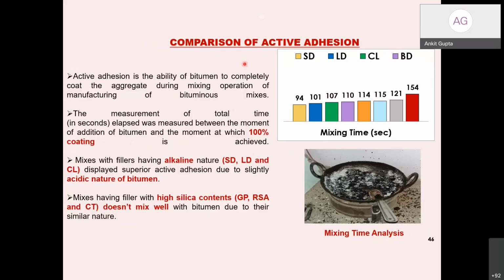Active adhesion is the ability of the bitumen to completely coat the aggregate during the mixing operation. When we mix the aggregate with the bitumen, how fast they coat the whole aggregates with the bitumen, that is the time of coating, basically what we measure. Obviously it is a visual test that we do in the lab. The total time elapsed was measured between the addition of the bitumen and the moment at which 100% coating is achieved.